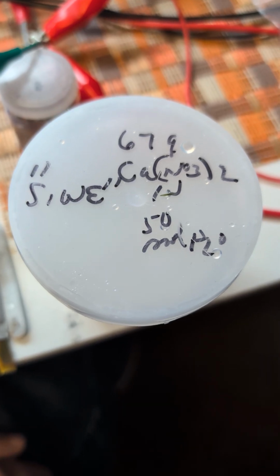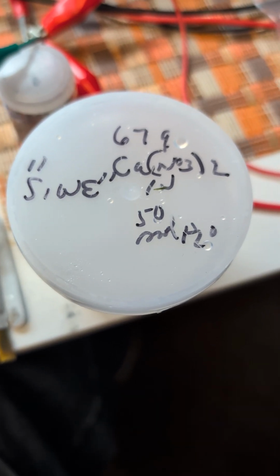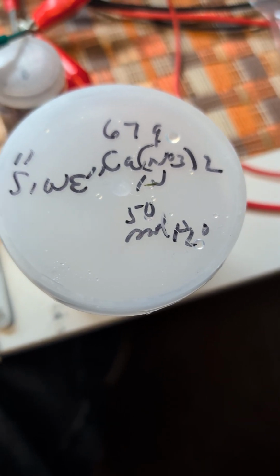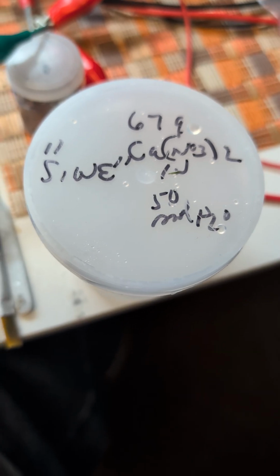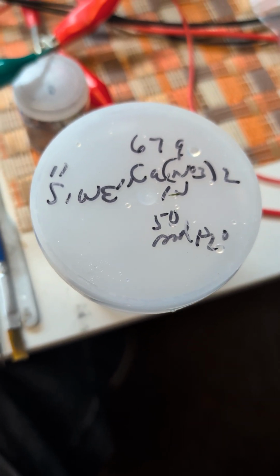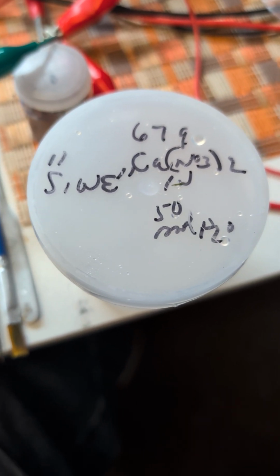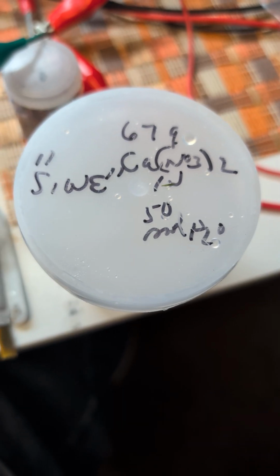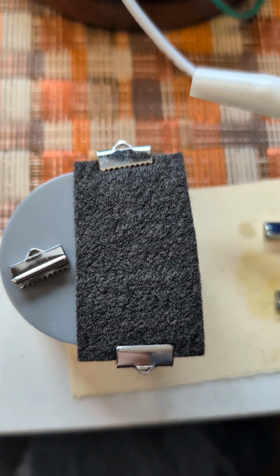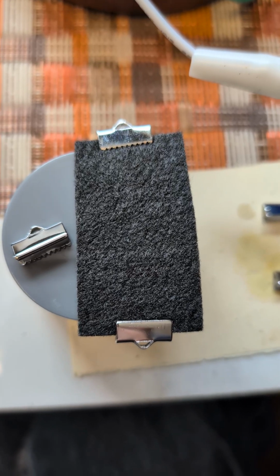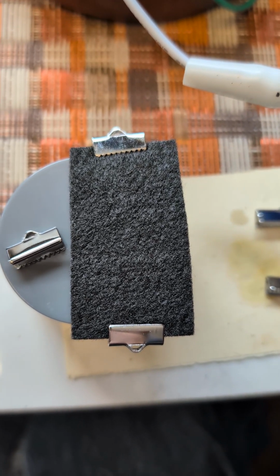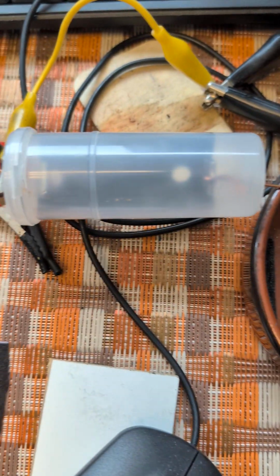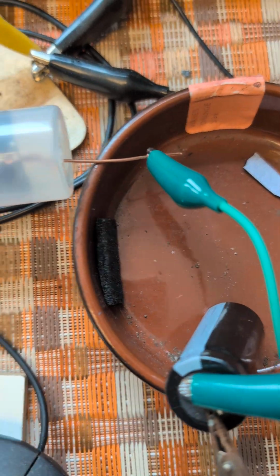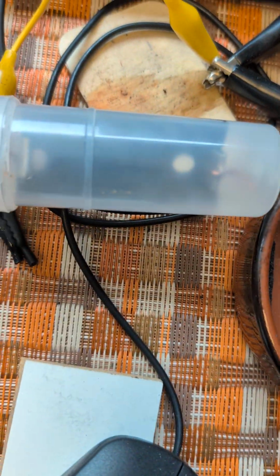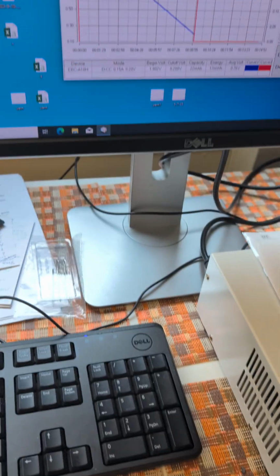It dissolves very readily. We also have sodium nitrate, and we'll be preparing sodium perchlorate, which is incredibly soluble. It's like 17 molar at 20 degrees Celsius. But right now, that's calcium nitrate. And we immerse the pad in the calcium nitrate solution. I leave it overnight, gently blot dry, and then attach to the copper leads, contacts, and then we run this.